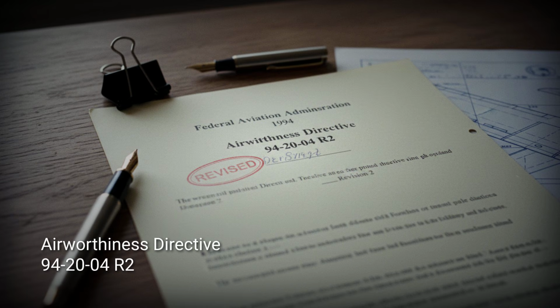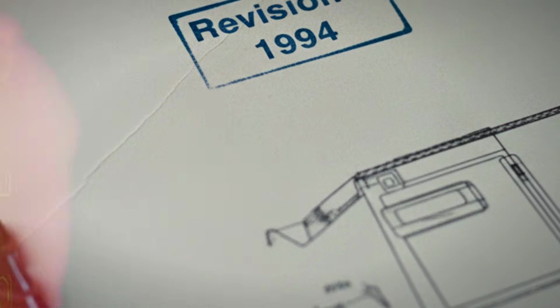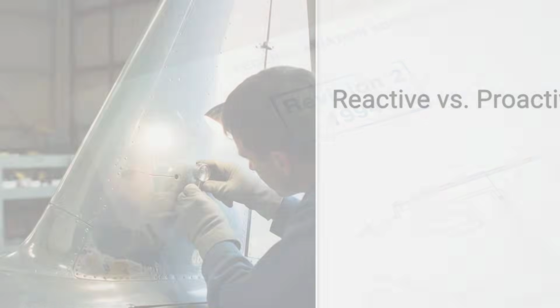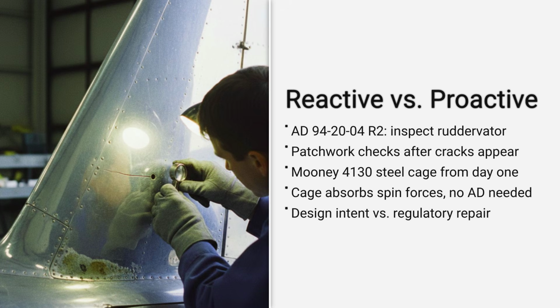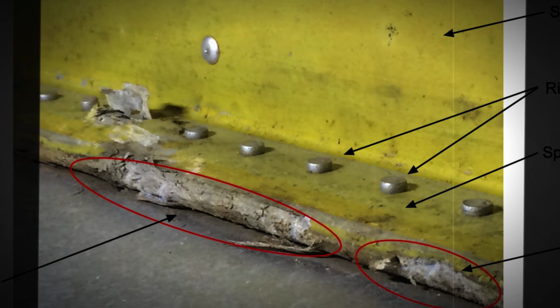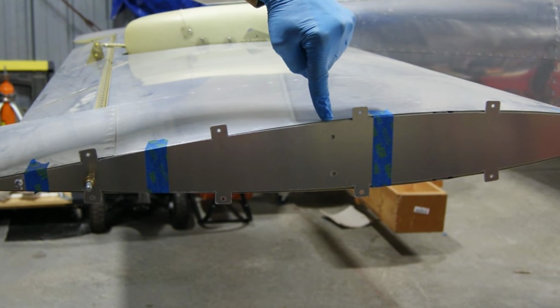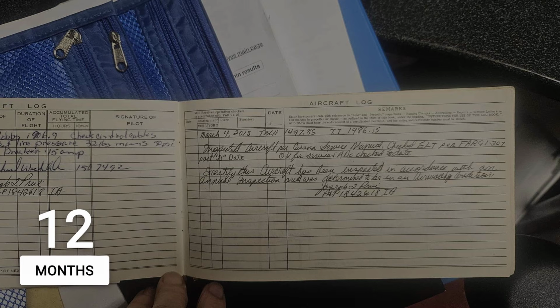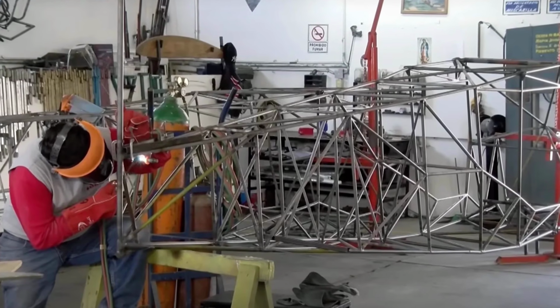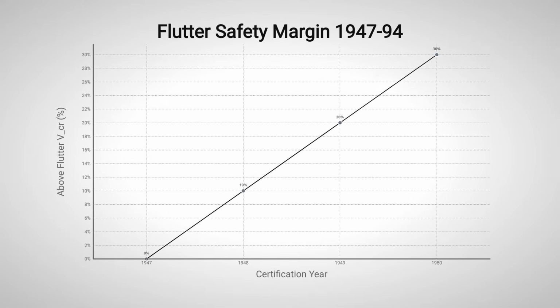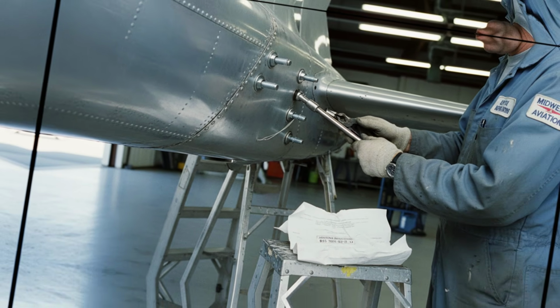FAA Airworthiness Directive 94-20-04, Revision 2, landed like a verdict. The directive's language is blunt: inspect every ruddervator for fatigue cracks, bolt hole elongation, and the first hint of failing magnesium skin. Stainless steel reinforcement plates and lock washers are now mandatory. Inspections repeat every 12 months or 2,000 hours. Form 4500-15 becomes a permanent entry in the logbook, a reminder that ignoring the flutter envelope is gambling with the airplane's life. The FAA's fix was not a redesign, it was a patch, bolted on after too many Bonanzas lost their tails in sudden, catastrophic dives.